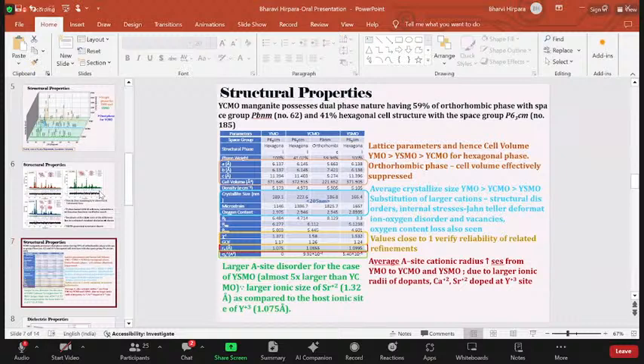This is based on the average A site cationic radius, which is also shown in the second to last row of the table. The average cationic radius increases from YMO to YCMO to YSMO, because of the larger ionic radii of the dopants, calcium and strontium, doped at the yttrium site. Also, we can see that the average crystallite size of YMO is the largest, then YCMO, and then YSMO.